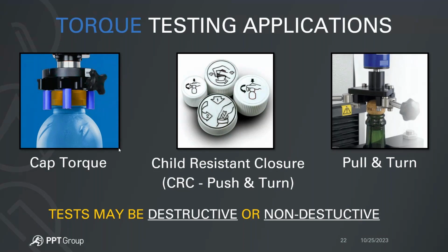That same process. And then obviously there are also the finals. Let me back up just a couple. I did mention three types of cap torque testing. The final is we use the term crossing the threads, right? Testing to destruction. How much torque do we need to apply before the sample just completely fails, where the cap just spins without actually tightening? So there's essentially just a destructive test to see exactly what the ultimate maximum torque is before the sample is destroyed or it crosses the threads and just spins freely.